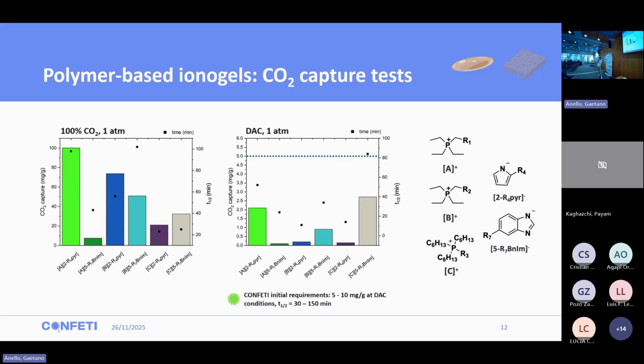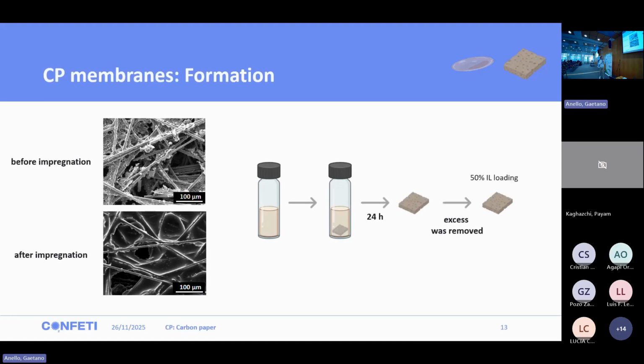So observing this limitation of the polymer ion gels, we decided to move to the second approach, that was to use carbon paper as a solid support. The procedure is really simple. It's just immersing the carbon paper in the ionic liquid for 24 hours and then removing the excess, achieving a loading of 50% of ionic liquid. Here we put two different images. The first is the carbon paper without the ionic liquid, where you can observe the porosity of the material, and the second one after the impregnation, where you can observe that all the pores are filled with ionic liquid.